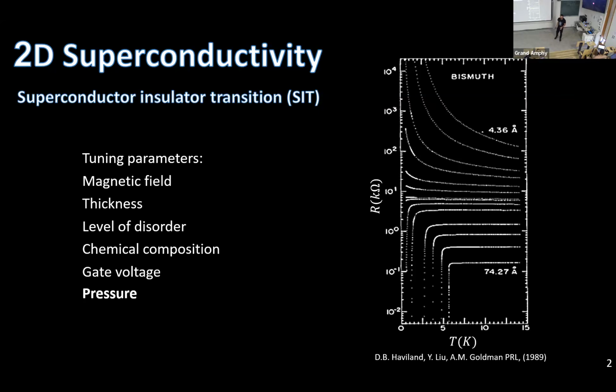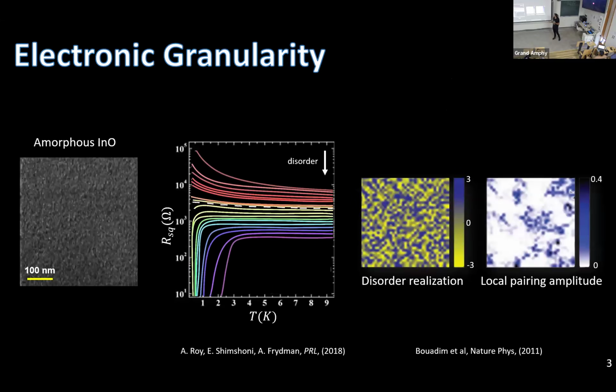There are multiple ways to explain this quantum phenomenon. One of them is the Bose-insulator model, when you have a granular system. But not just actual granular systems fit this model. Even amorphous samples like amorphous indium oxide, which will be the main material we did our measurements on, show some electronic granularity with adding disorder to the system. Electronic grains of superconductivity, island superconductivity, emerge in this amorphous indium oxide, giving us those granular grains of superconductivity.